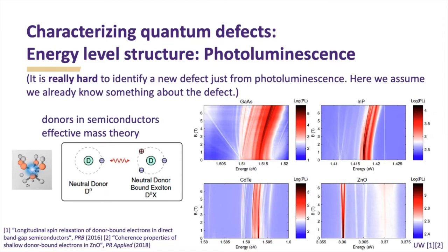So this is an example of my own work on donors in semiconductors, where we have a donor just like phosphorus in silicon. When you're at room temperature, that electron is donated to the conduction band. But if you go to very cold temperatures, and these measurements were taken at 1.5 Kelvin, what happens is that the electron is bound coulombically to the positive charge of that dopant. So now you have what looks like a hydrogen atom. It's an effective mass solid state hydrogen atom.